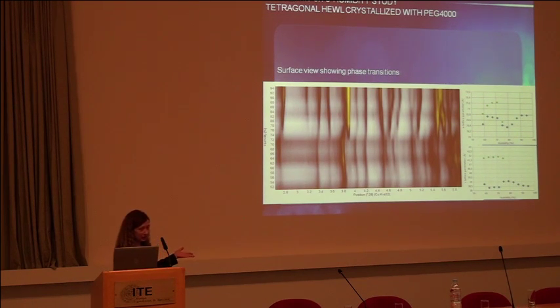After indexing these profiles, the space group remains the same, it's a tetragonal structure, but we observe this drastic change in the A and C lattice parameters. Look at this jump. And afterwards, when we solved the structure, we saw that basically the lattice undergoes a dramatic phase transition upon humidity variation.